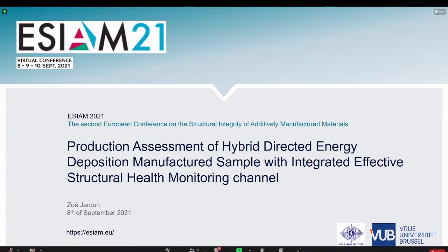And since you mentioned that the inner surface roughness is somehow relevant, did you also consider these electrochemical methods for cleaning out inner surfaces and also getting rid of this residual powder that might get stuck inside these capillaries? Indeed, we have done some studies on the post treatments that can be done on the capillary channel. For the detection of a crack, it's not needed to apply this chemical etching because we can reach quite low roughnesses with the drilling operation. Now, if we want to go to the crack localization, it relies on the propagation of pressure waves in these channels. And there, the propagation velocity is affected a lot by the obtained roughness. And there it's needed to post-process the part with something like chemical etching.